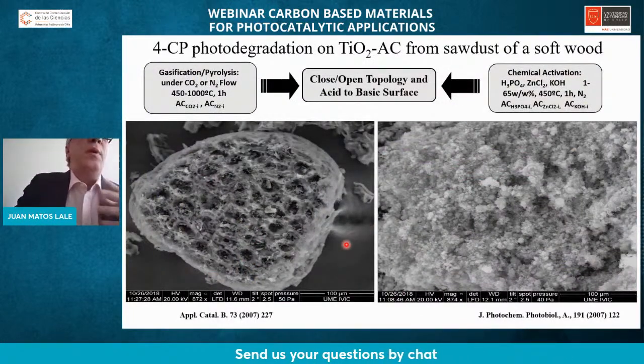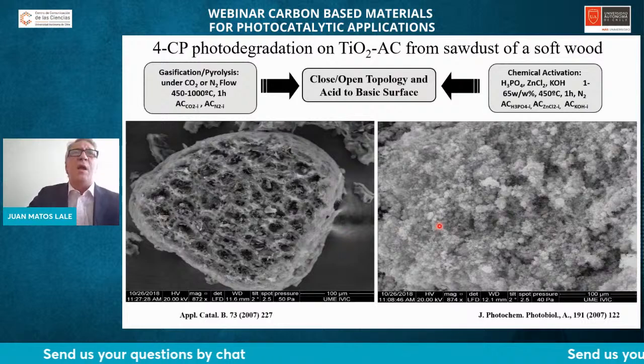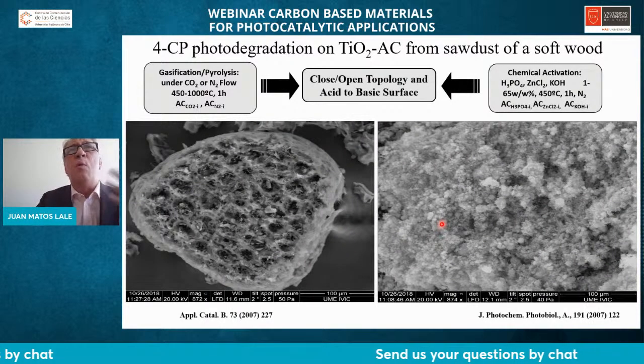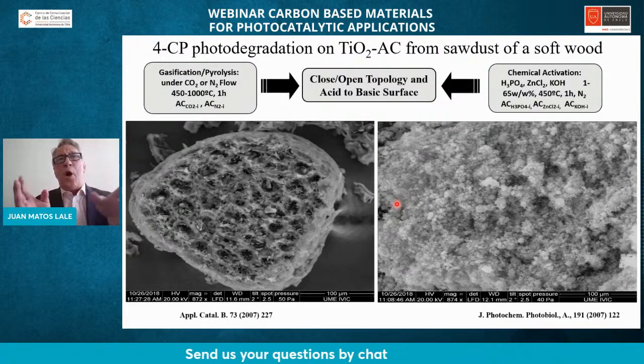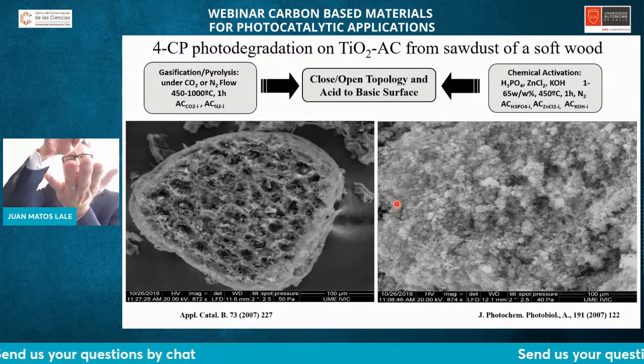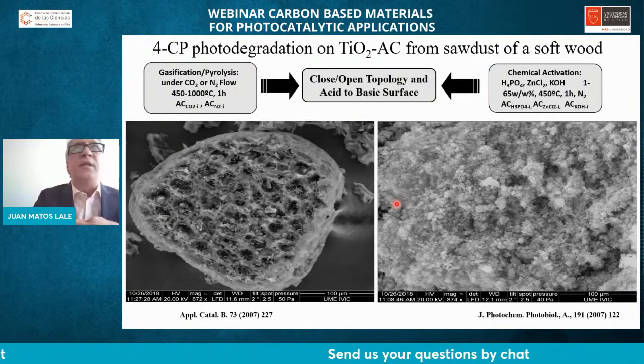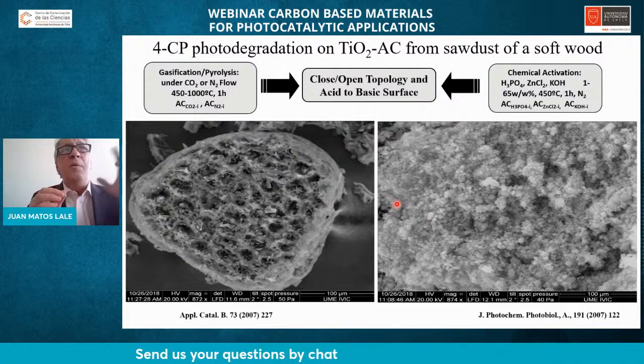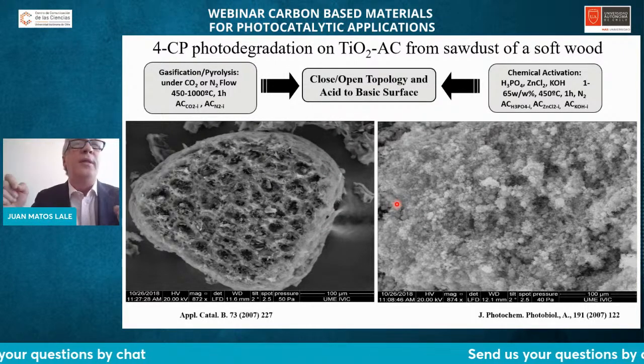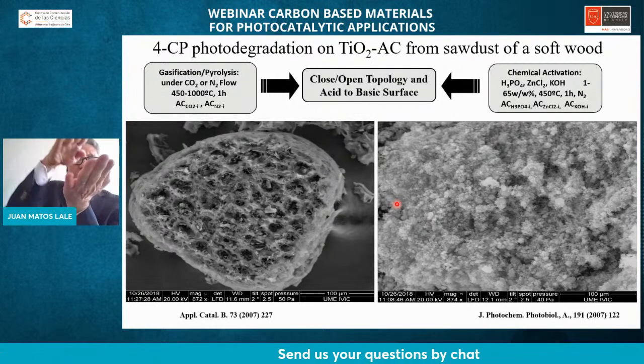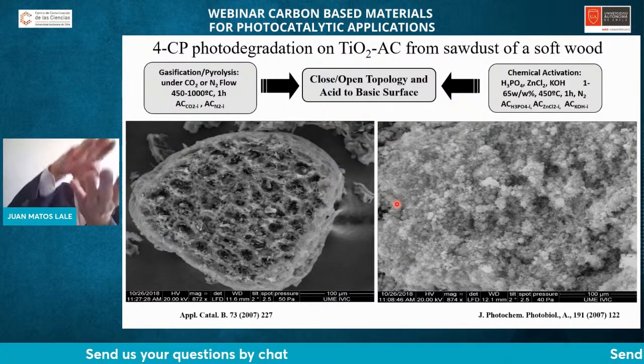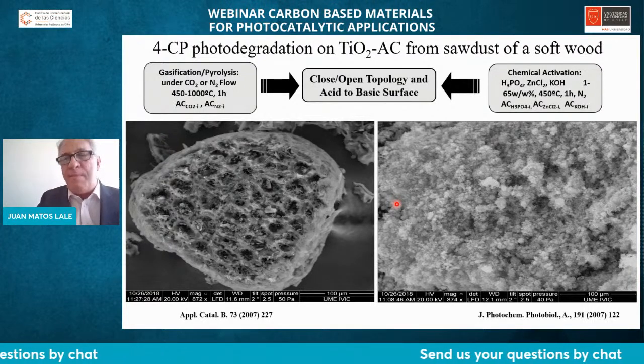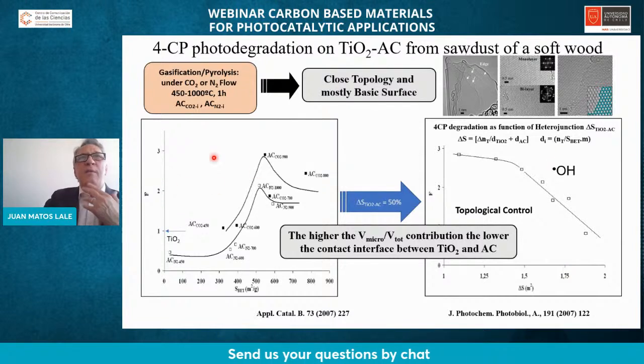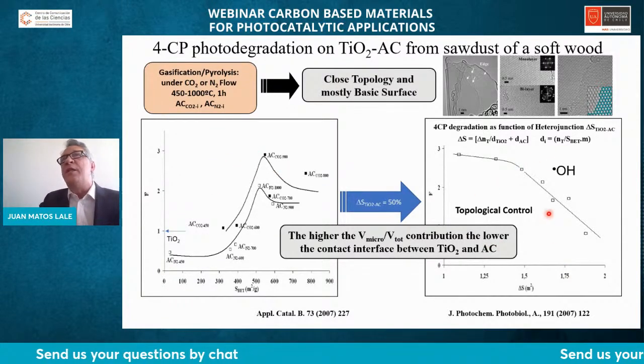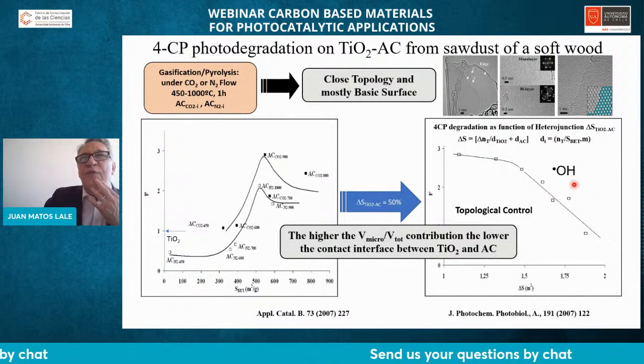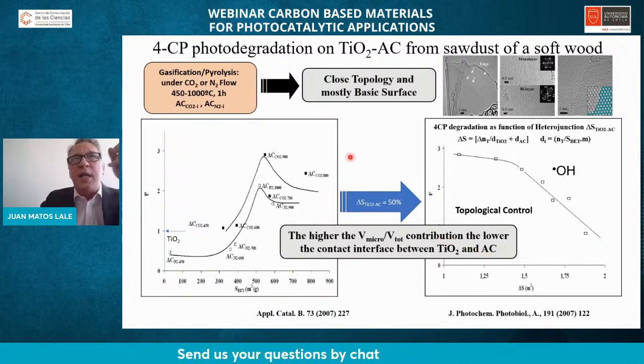So what's going on? We have a long history using porous carbon materials in photocatalysts, more than 20 years working with this. We are able to control the topology from very closed topology, even close to molecular sieve, with distances between the layers in the order of 0.5 nanometers, very close to graphite at 0.33 nanometers. So we are able to produce very closed topology carbons, or even more open topologies, and introduce functional groups. And depending on this, we are able to achieve different mathematical models that deal with the production of hydroxyl radicals, and we are dealing with the topological control.